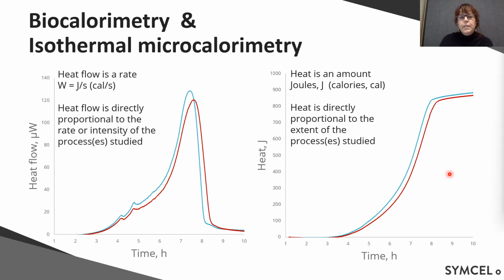So if we look at the data output that will come from a microcalorimeter, we will measure heat flow. I mentioned we have a heat flow calorimeter. Heat flow in microwatt, and we measure this in watts. A watt is equal to joules per second. So it means it's the rate, how much heat we are producing per time unit. And if you are from the USA, you may call it calories per second instead of joules per second. Joules per second will directly go to watts, but if you use calories, you will say microcalories per second. You can translate this into watts.